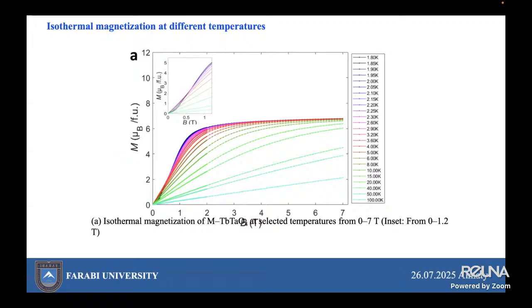As the temperature increases above, for example, here 3 or 4, the green, for example, linear to saturation behavior gradually disappears, and the magnetization becomes more linear. This more linear response to the applied field is characteristic of paramagnetic behavior, and the inset highlights the low field region up